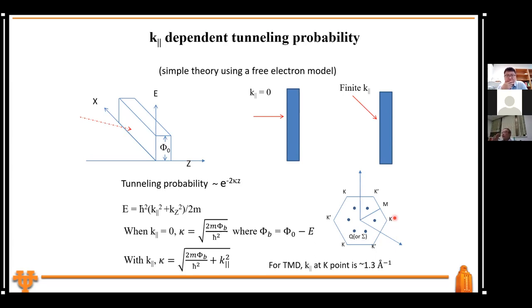When I gave this explanation at a conference, one researcher from Germany said, well, you've got to realize the spin structure is not free electron. This is a Bloch state. And it's an excellent question, right? But if you go to the original Tersoff formalism published in PRL, you'll find this K parallel comes in exactly like what I described here. And this is the reason: if you think about the Bloch state, you can decompose it into a superposition of different free electron states, with something like an umklapp process, adding some reciprocal lattice vector, right?